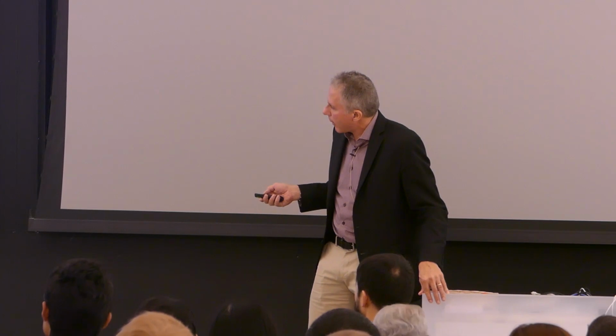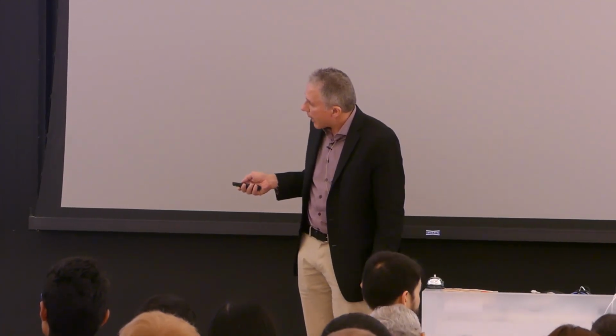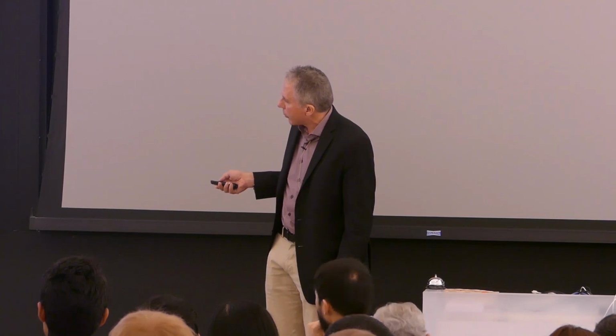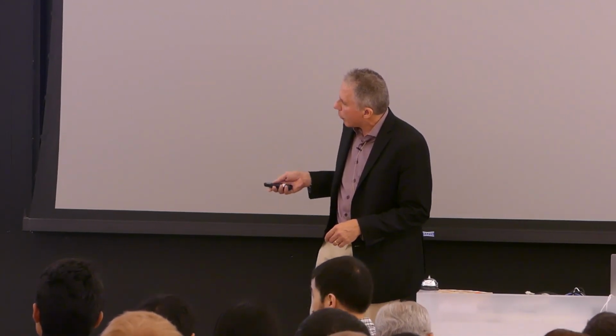Actually, this number is out of date. I should have corrected that. That's now 32.2% actually for the two junction cell. And earlier this year, Alta Devices, which is the company that we founded to commercialize this technology, set a world record for the first greater than 25% efficient module. So if you look at the current density, the current densities are comparable to the current densities from previous solar cells, but the world record was achieved by increasing the voltage through the photon recycling and extraction processes that I mentioned.